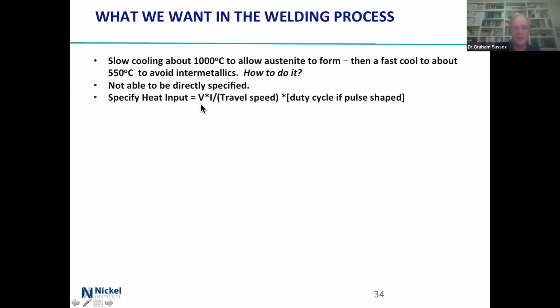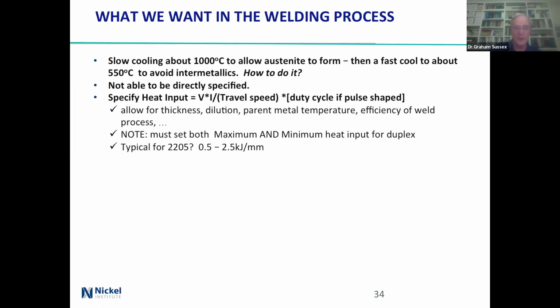But the heat input is just that, divided by the travel speed and the duty cycle of its pulse shape. That's not actually, it's an experience thing, and you write the procedure that will actually do it. You're going to allow for the thickness, the dilution, the parent metal temperature. If it's all cold, it's going to cool quickly, and the efficiency of the weld process, how much energy you're putting in and how it's getting transferred.